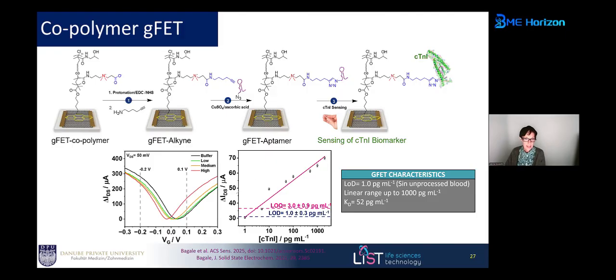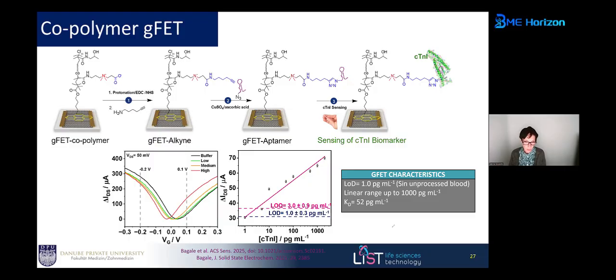And as you can see now from this curve here, when we do the measurement simply in full blood from a blood droplet, we can distinguish clearly between low, medium, and high cTnI levels, and we can even get calibration curves. If you look at these calibration curves, we have detection limits of around 1 picogram per milliliter, so clearly adapted for distinguishing healthy from unhealthy people, with a linear range increased up to 1,000 picograms per milliliter. I didn't show it here, but we scanned several blood samples, so we are now in a position, in 2-3 minutes using these devices, to take a sample from a fingerprick like you would do for a glucose sensor from a patient and detect cTnI in the full blood.